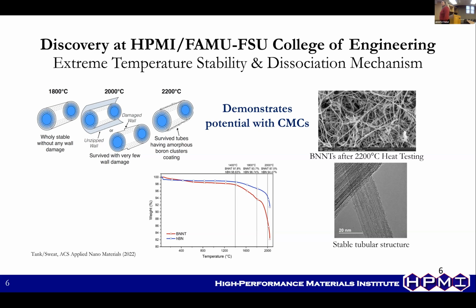So a student, Mehul Tank, last year, he did the decomposition of BNNTs and found that they're pretty stable up to about 1800 degrees C in inert environments, briefly stable to about 2200 degrees C, and observed a stable tubular structure via transmission electron microscopy, or TEM, after exposure to 2200 degrees C heat testing in a real manufacturing graphite furnace. So not just in a TGA or something like that.